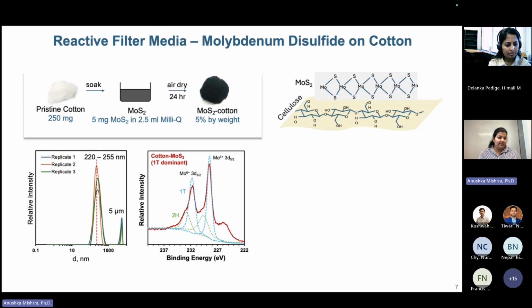So we are looking at the nanoparticle size after we have coated it on the cotton. We see that there are 220 to 255 nanometer particles. We also see some aggregates, but the number of these aggregates seemed lower, did not seem to be a bigger fraction of the material that we coated.